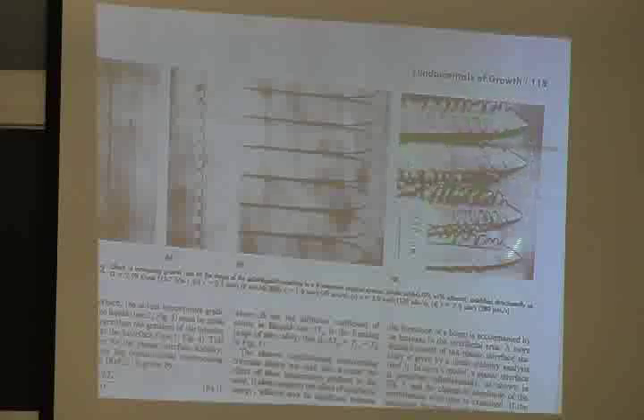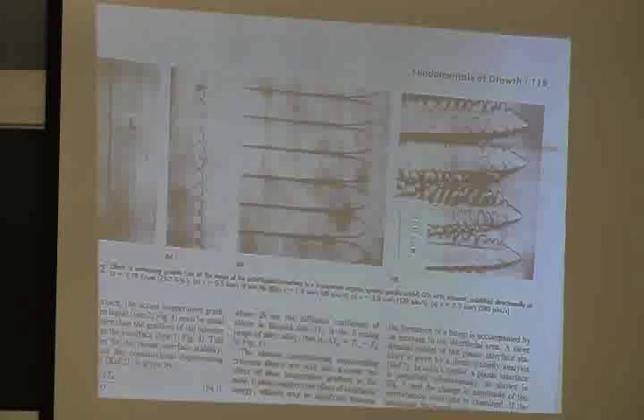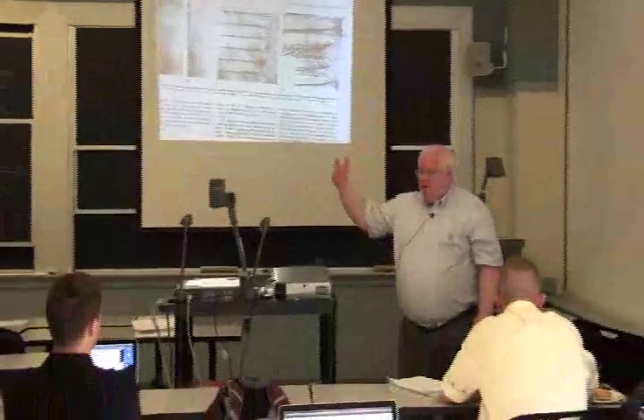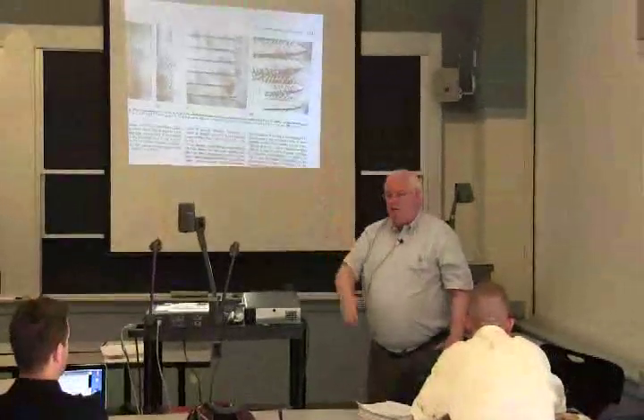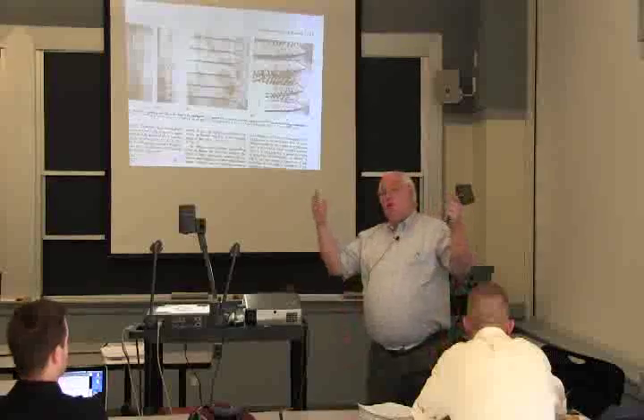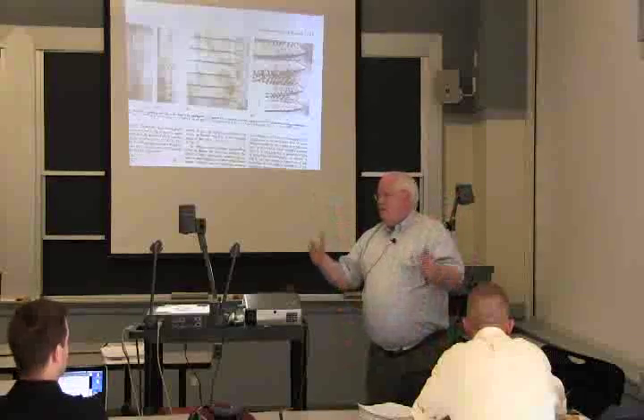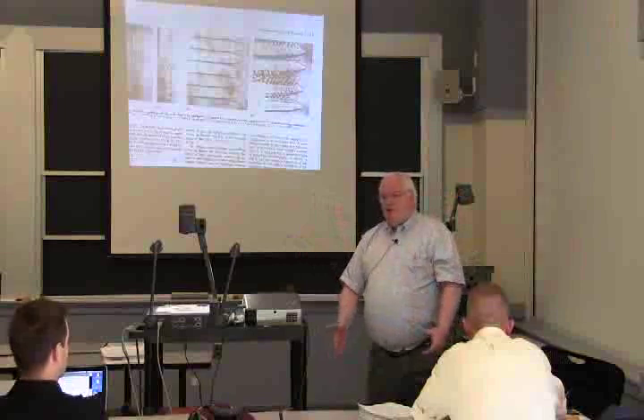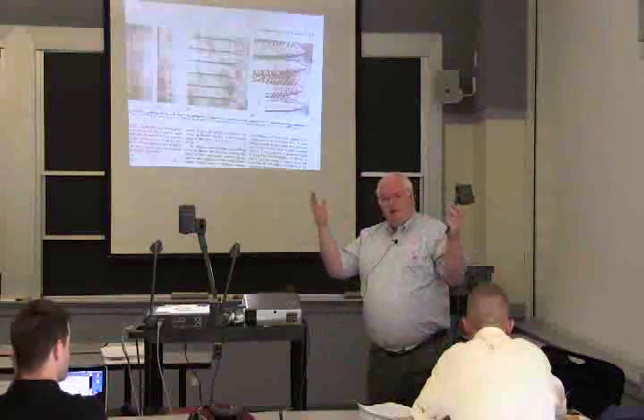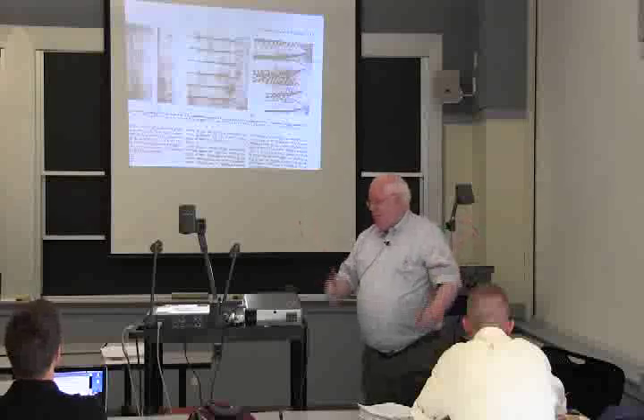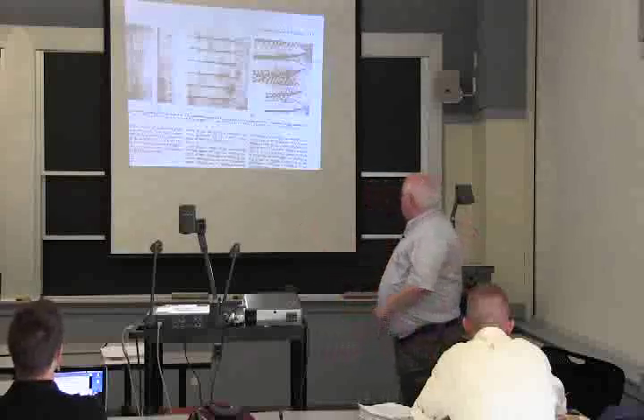When it gets really unstable, you get dendritic growth, with instabilities along the side creating the dendrites. Those dendrites create porosity in your casting because the liquid can't get past all those little branches. It's kind of like in a snowfall - underneath the fir tree, you don't have any snow on the ground because all the snow got caught up in the boughs, so it doesn't reach the ground.